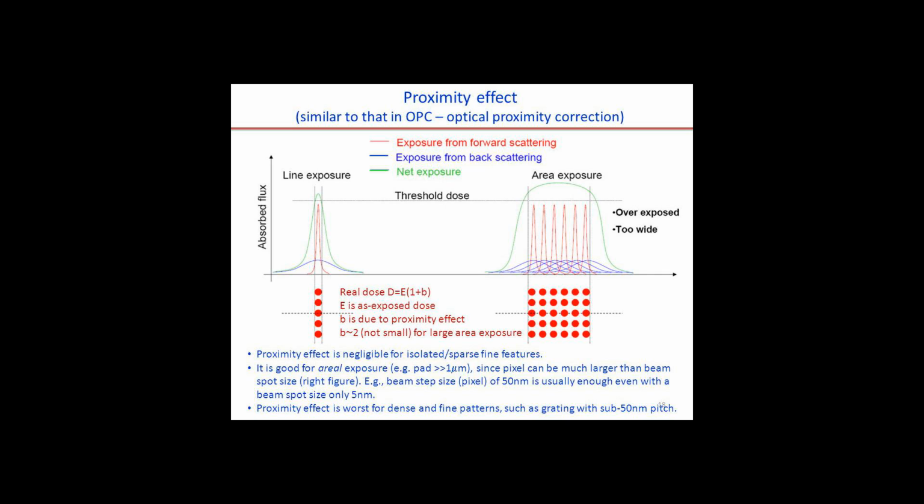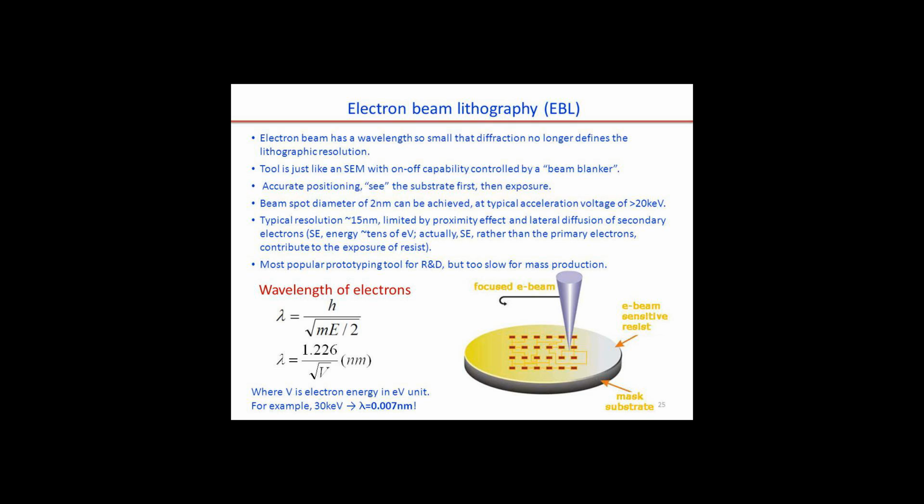This is limited mainly by aberrations and space charge. However, the feature resolution limit is determined not by the beam size but by forward scattering or effective beam broadening in the resist, while the pitch resolution limit is determined by secondary electron travel in the resist.